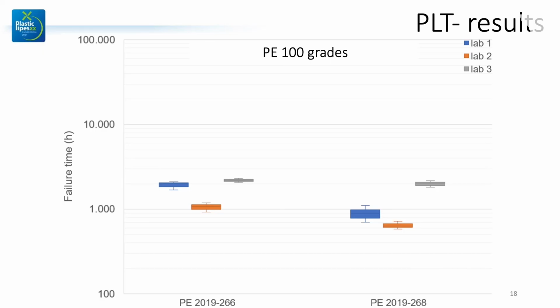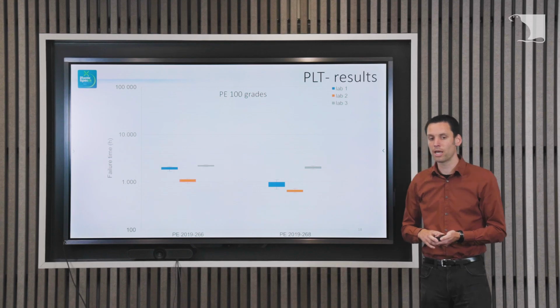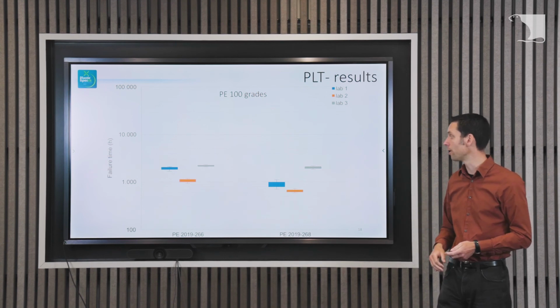What is the agreement between these three laboratories, Kiwa, SKZ and TGM, about our failure times? How do they correspond with each other? So that's what I'll show here. Here you see two materials, coded 266 and 268, and the failure times in these three labs for the P100 grade. And this is tested with Arkopal. So you see that the failure time is a little bit higher because Arcopol isn't so aggressive to the polyethylene.